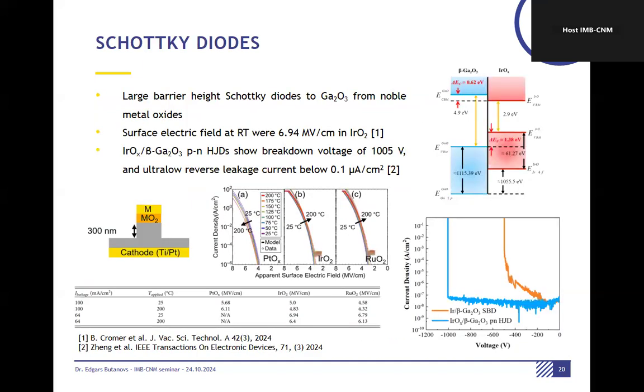And the last thing before I move to the results, it's some interesting thing about Schottky diodes and what I've noticed in the last few conferences I went to. It's very interesting to make Schottky diodes with noble metal oxides, such as platinum, iridium, which I already mentioned. So there are quite good results, I think, from very simple device structures. Let's say I will talk about iridium oxide. If you deposit a slightly oxidized Schottky junction, you can get quite good results in, let's say, electric field capabilities. These are quite recent results, so it's a very fresh thing.